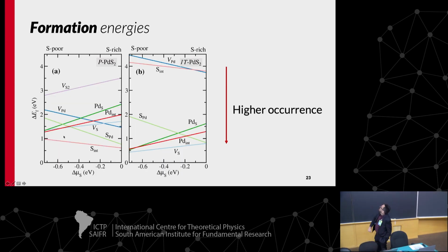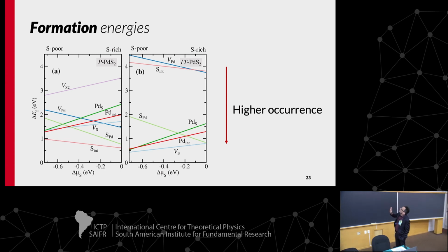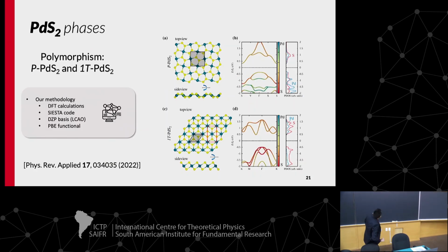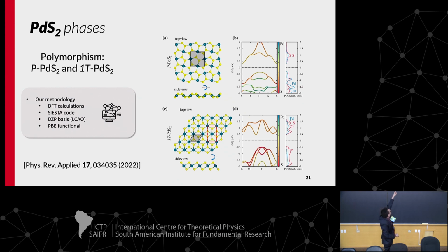Yes, the change is very different because the geometry of the defect and the material is very different. Let me show here. In the 1T phase, all the sulfur atoms are bonded with the palladium, but in the pentagonal phase you have sulfur-sulfur bonds, so we have different bonds. If you include one more sulfur, it is very different to include it with sulfur bonds here and sulfur bonds there. The bonds here are different. We have a sulfur here when we don't have one there.